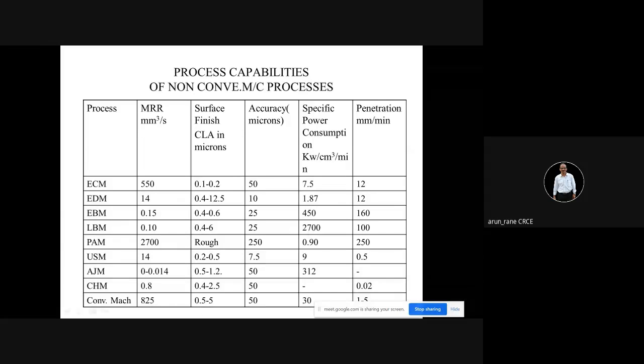So by now you are aware of all these machining processes. Now, this is your conventional machining, that is your normal machining. In this machining, you have material removal rate (MRR) of 825 millimeter cube per second. Then surface finish is around half a micron to 5 microns. Accuracy you can get is 50 microns. Consumption is 30 kilowatt per cubic centimeter per minute, and then penetration is around 1.5 millimeter per minute.